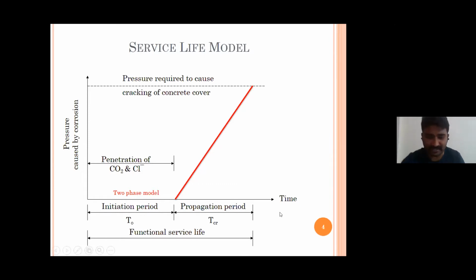And people in the 1980s believed his theory and started implementing it on existing structures. On the surface, if you take the core and start analyzing, we came to know that there is corrosion, but still we are not able to see the cracks on the surface. And people started doubting this theory. According to this theory, once the corrosion initiates, there should be a corrosion crack within a year or so. But actually, the predicted service life is lesser than the service life of that bridge or structure. Then people started thinking there might be something else.